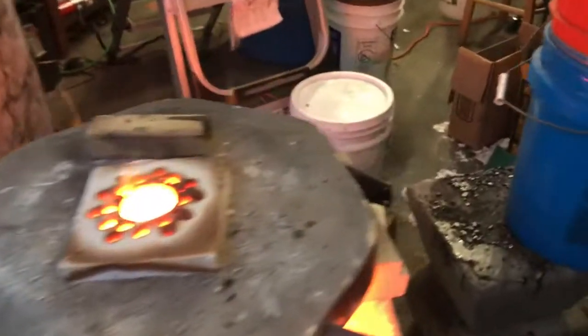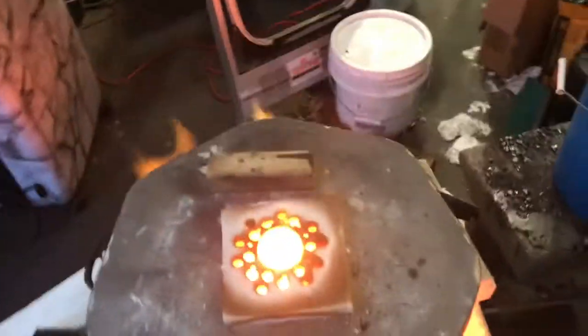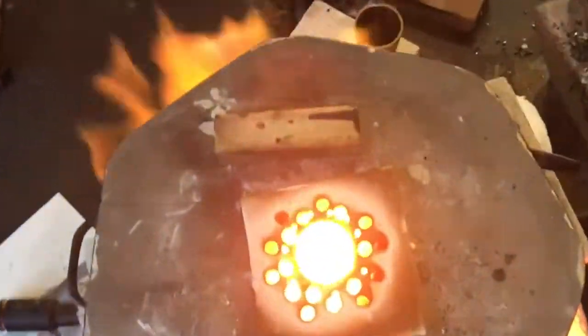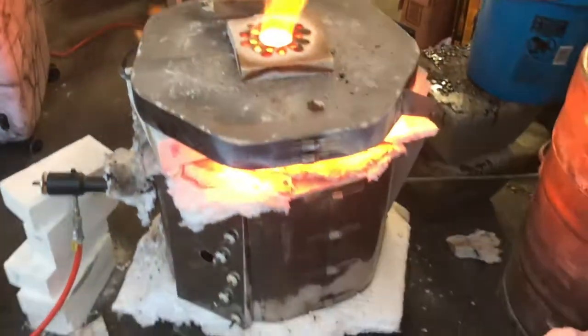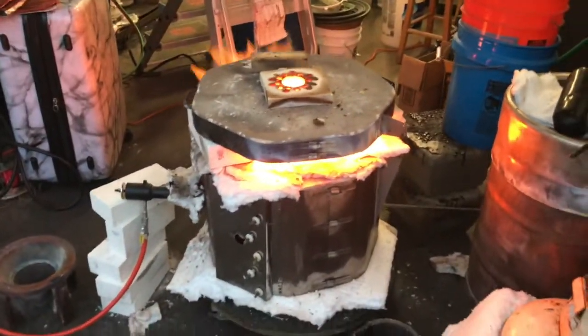In the middle of the project, the electric oven broke down, and so we tried an alternate process with a propane oven, but that appeared to be risking some unacceptable losses of precious metals, so that was abandoned, and another oven was ordered, and then work resumed. These cupels were kind of small for the amount of material that we were running, so larger cupels were ordered.